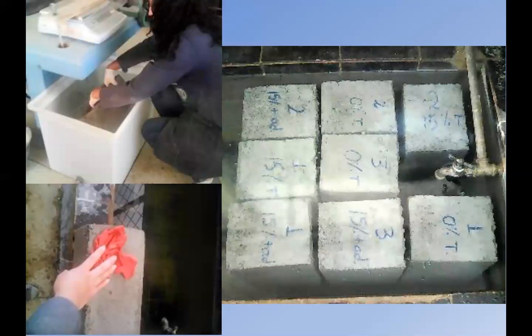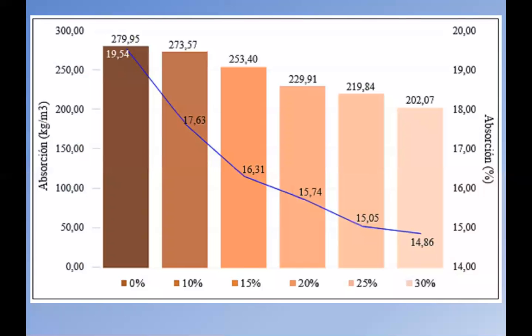For comparison purposes, compression and absorption tests were conducted on specimens that were made with only 25% PET, and some replacement samples in which the total amount of pumice was replaced by PET plastic, and hollow concrete blocks. For commercial use, they have low resistance compared to the blocks that were generated. It can even be determined that the specimens with PET that do not contain additive and those that do not have pumice could be used in construction, coinciding with studies where blocks containing plastic, due to their resistance, cannot be used in structural masonry. Several studies mention that using recycled plastic aggregate in concrete reduces costs.